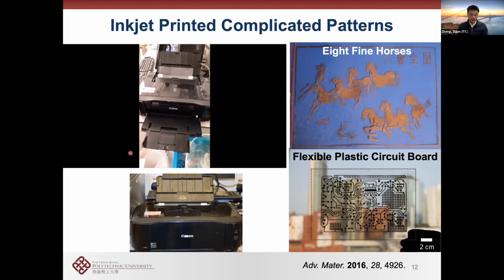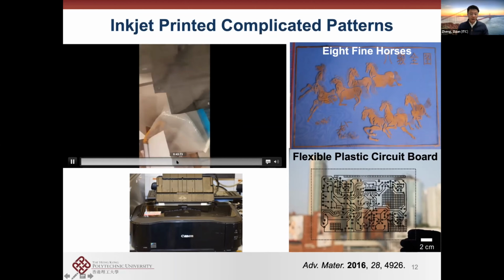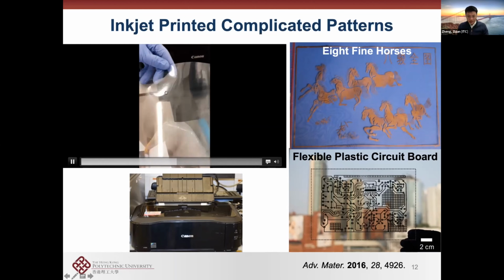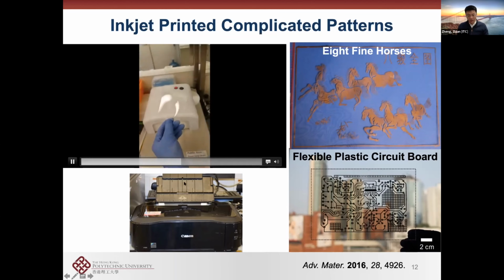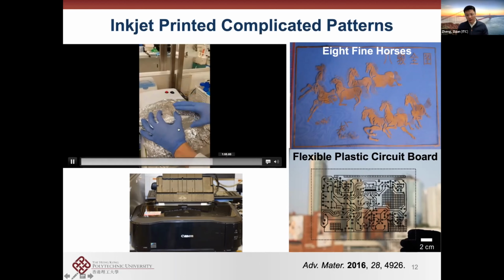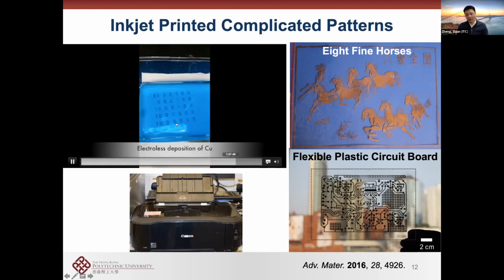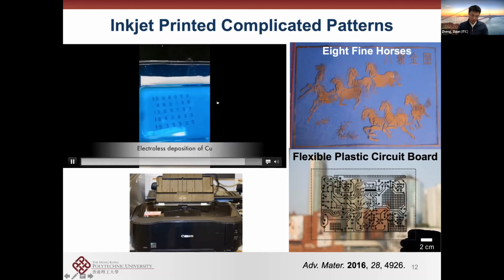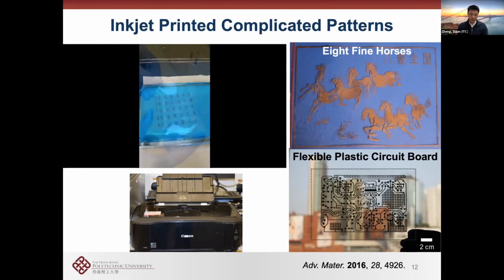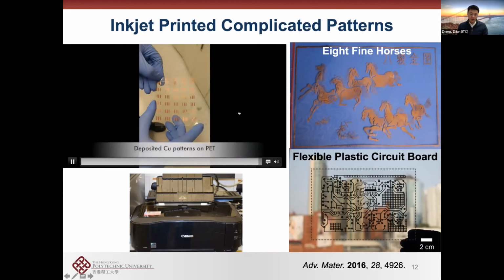So after you print it, let me see if I can speed up a little bit. You don't really see much, just a little bit of pattern. So we go through a curing process to cure the material under UV. And then we place this polymer onto the electroless deposition bath of copper to grow the copper. And this growth takes about minutes to tens of minutes.